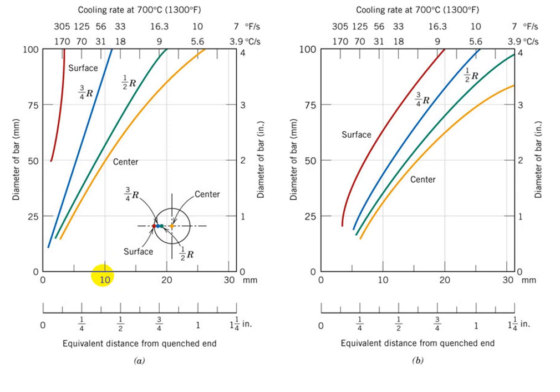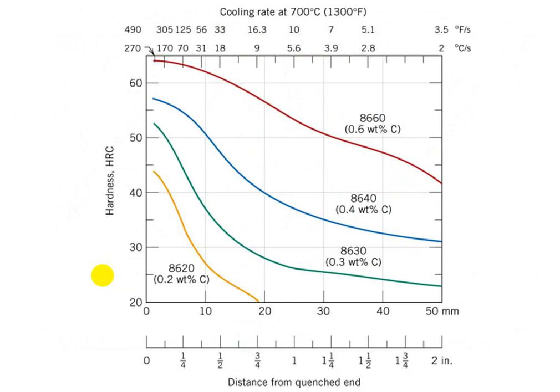And then I go back to this. Let's say for example this is 8640 alloy. 8640 is here, 10 millimeter, I go here, and you can say okay the hardness is around let's say 52. So this is how you calculate it. It was two inches, not one, but I use these two charts to get the value.